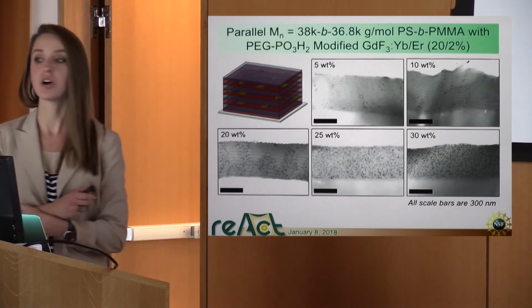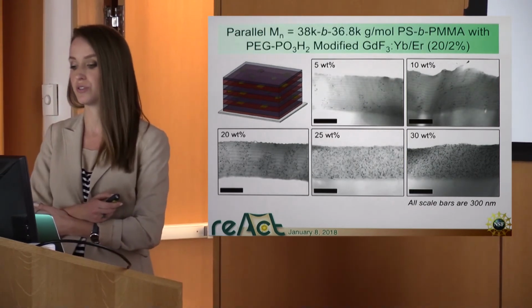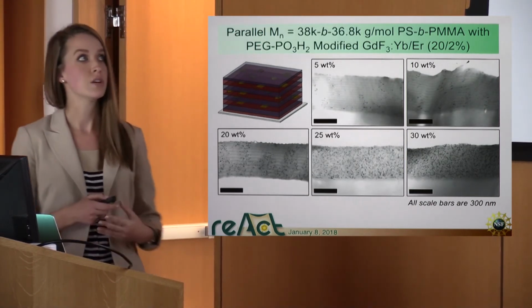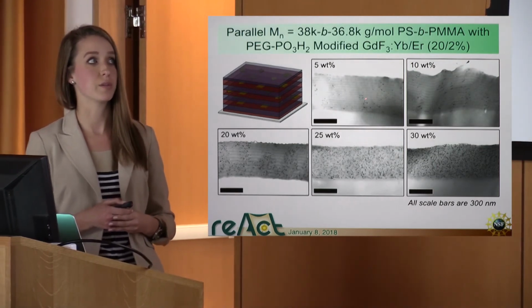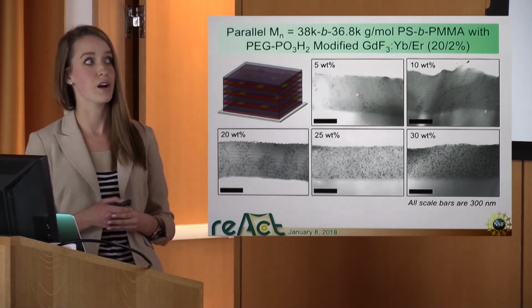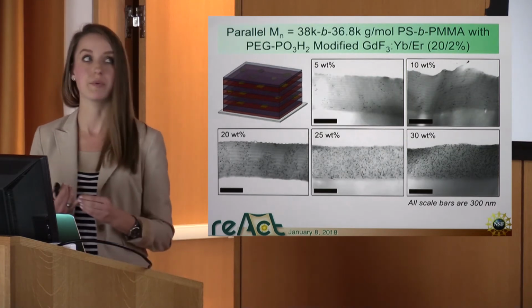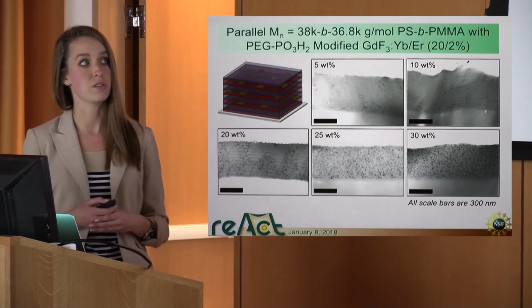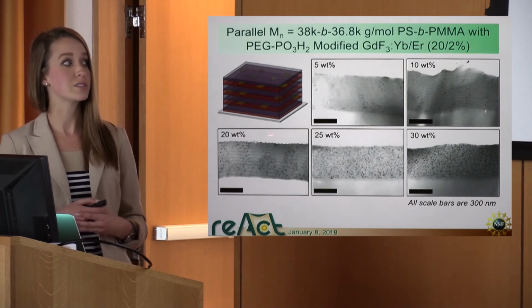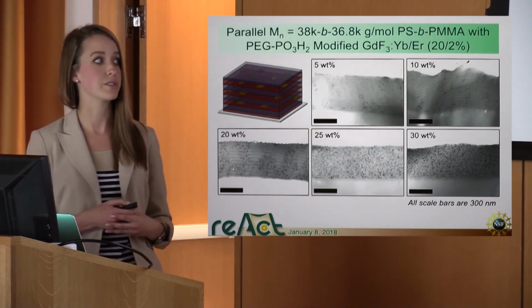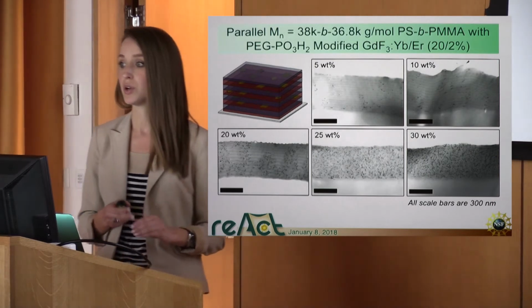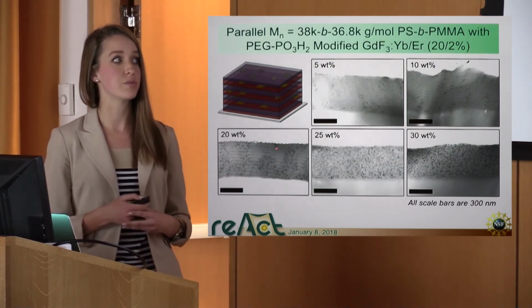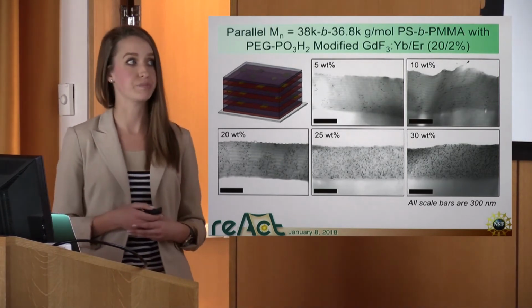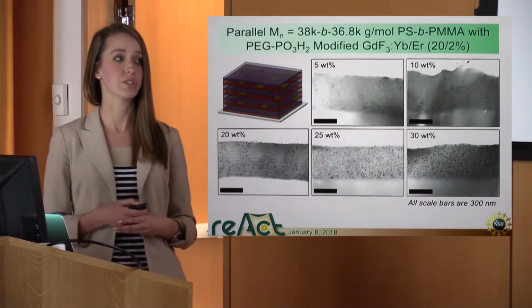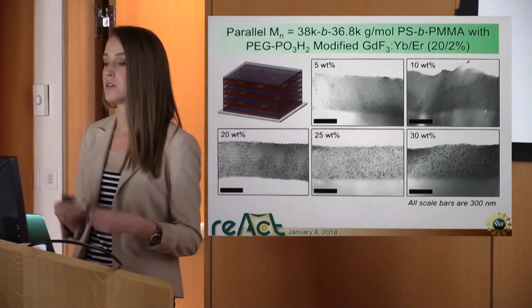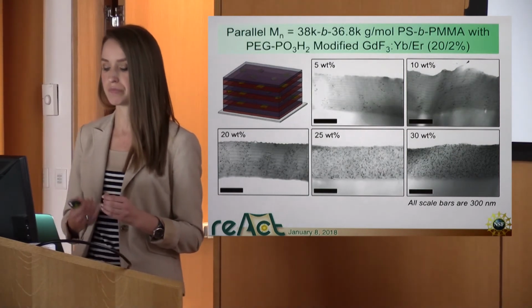And so here we're looking at cross sections of these images with increasing loading of the platelets. From 5 weight percent, we see that the particles are segregating to this lighter stripe, the lighter domain, which is the PMMA. At 10 weight percent, we see that effect as well. However, when we get to 20 weight percent, we see areas of disorder where the particles start to be randomly oriented, and then we do see regions of lamellar formation. And then once we increase loading to 25 weight percent and then 30 weight percent, the particles are randomly oriented.